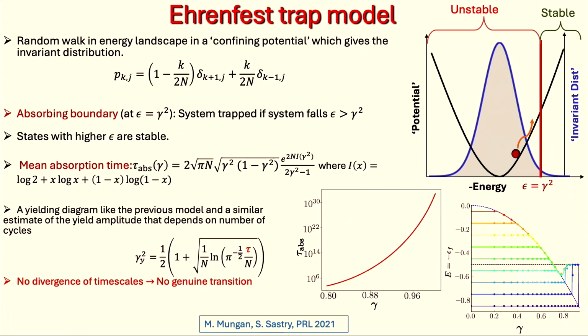Again, I can take this model and look at what the state of it is as a function of the number of cycles. And again, I get a yielding diagram which looks very similar. And once again, there is no genuine transition, because if I wait long enough, I will eventually get trapped. But the way to have a more realistic and interesting description is to say, even if I am at a sufficiently large or low energy so that I'm stable with respect to a given amplitude of strain, is it possible for the system to escape out of these stable states, the absorbing states?